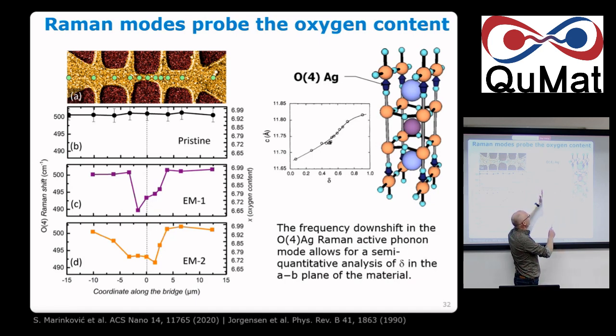And as delta increases, so you remove more atoms, the c-axis of the unit cell increases, so it becomes a softer mode, and the frequency goes down. So it's very easy to detect how much oxygen you have. So we did Raman at these green spots. In the pristine sample, everything looks nice. You can even detect how many oxygens you have. Once you electromigrate, you see that it goes down.